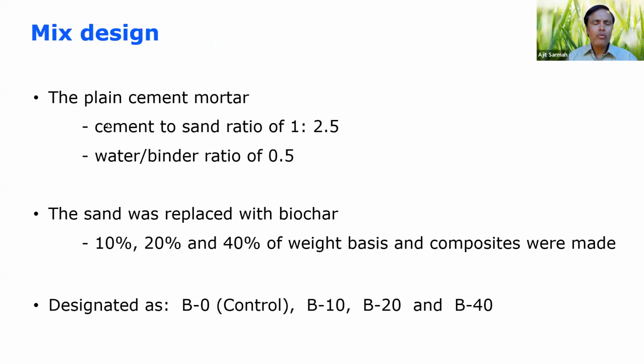Then we did control, any experiment you want to do control. So we looked at plain cement mortar, cement to sand ratio, water to binder ratio, and we replaced sand partially with biochar. We had a 10% biochar, 20% biochar, 40% biochar instead of sand. Some of the sand, because to produce concrete, you need what?